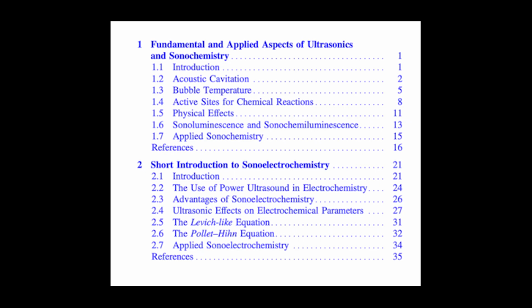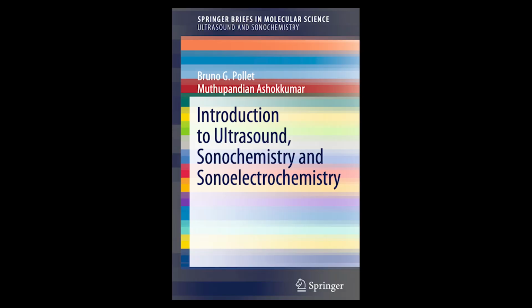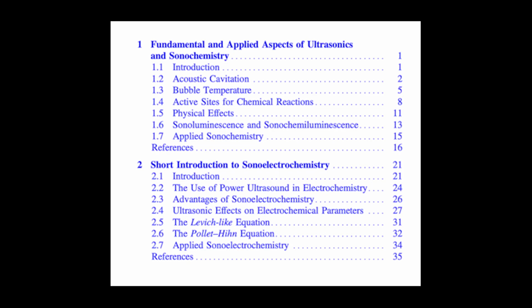The implosion, that's the main event. That's our engine room. The collapse is so fast, nanoseconds, maybe picoseconds, that it's essentially an adiabatic process. Adiabatic, meaning no time for heat to escape. Precisely, no significant heat exchange with the surrounding bulk liquid, which is still relatively cool. All that kinetic energy of the collapsing bubble wall gets converted almost instantly into heat and pressure inside the tiny trapped gas vapor cavity. And the conditions created are?